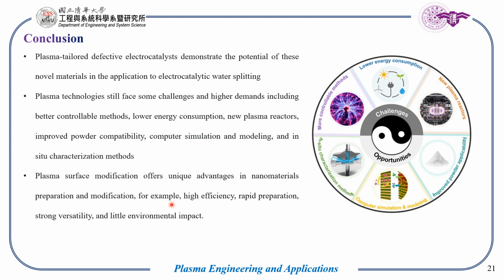And the efficiency has been significantly increased, because they create some surface defects, and also some vacancies and different kinds of heterojunctions, which lead to the creation of many active sites. These active sites react with the surroundings, providing much better catalytic efficiency.